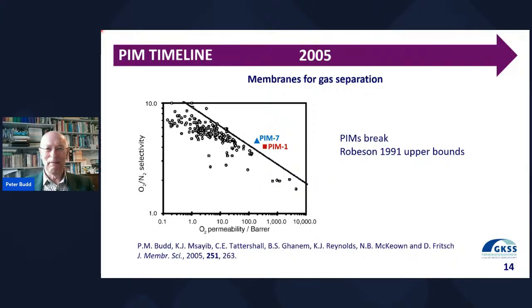And those of you involved with membranes for gas separations will probably be well familiar with the Robeson plots. Robeson, back in 1991, collected together all of the data that were then available for polymers for gas separations. And he plotted for a variety of gas pairs on double logarithmic scales, selectivity against permeability, and simply drew a line through the best performing points. And that represented in 1991 the limits of performance with polymeric membranes for those particular gas pairs. The example we have here is the oxygen-nitrogen gas pair. There are a number of others. And what we see is that PIM-1 and PIM-7 broke that upper bound, that we not only had a relatively permeable polymer, but that it was more selective than had been thought to be generally feasible at the time.